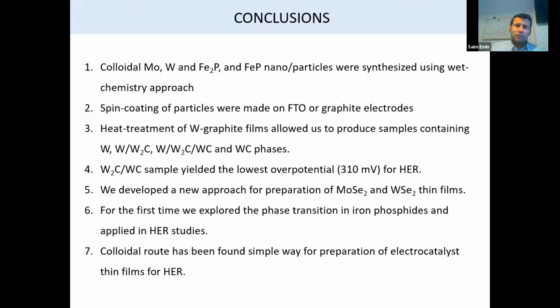In conclusion, I would like to say that we used colloidal approaches to synthesize molybdenum, tungsten, and iron phosphide. Some are nanoparticles, some are microspheres. I didn't show all the data using wet chemistry approaches. Spin coating of particles was made on FTO, fluorine doped tin oxide, or graphite electrodes.